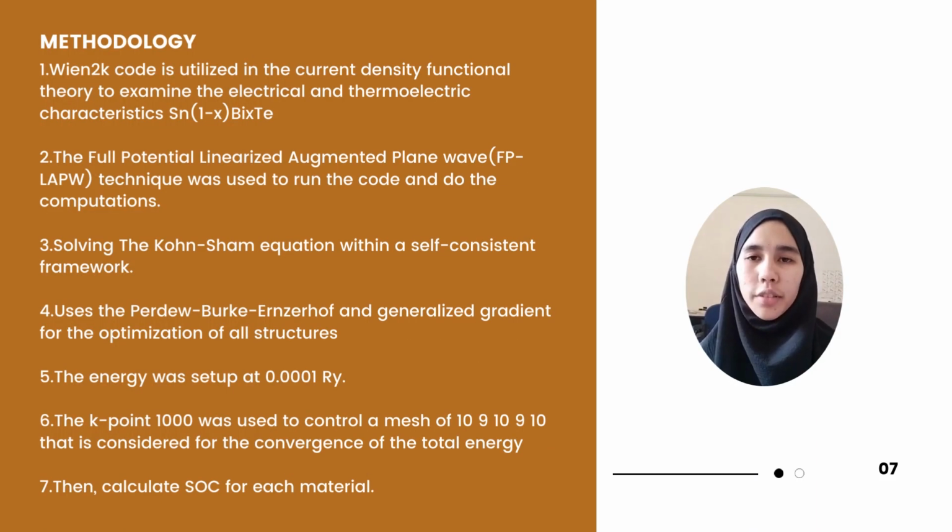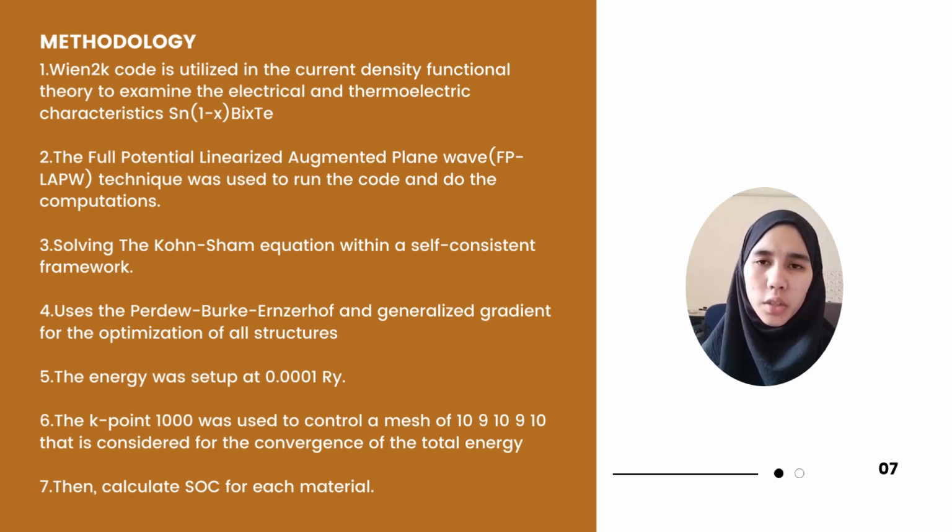Alright, so how to conduct this research is, firstly, WIEN2k code is utilized in the current density functional theory to examine the electrical and thermoelectric characteristics. Number 2 is the full potential linearized augmented plane wave technique was used to run the code and do the computations. Number 3 is solving the Kohn-Sham equation within a self-consistent framework, or we call it SCF.